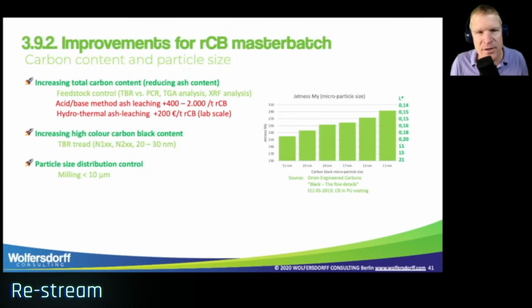The second stage of improvements for the recovered carbon black master batch is increasing the amount of the high color carbon blacks. So we need to see, this is about the particle size and the microparticle size. Where are high color carbon blacks? And these are predominantly in the truck tire tread. So this is just the tread which has ASTM N100 or N200 range of carbon blacks. And they typically have a microparticle size between 20 and 30 nanometers. The smallest the furnace process can produce is 20 nanometers.